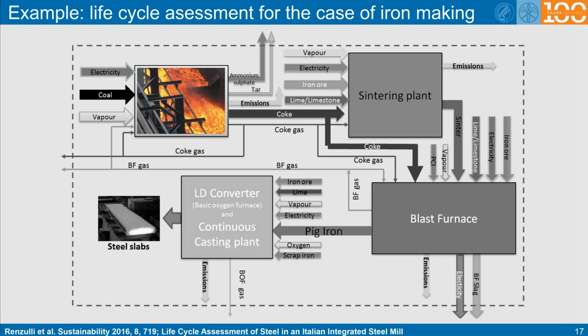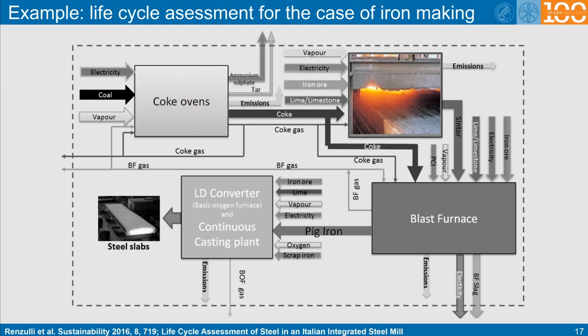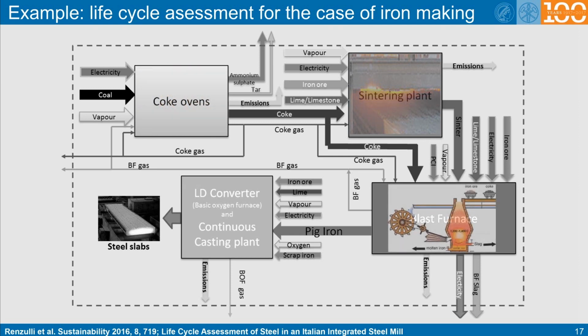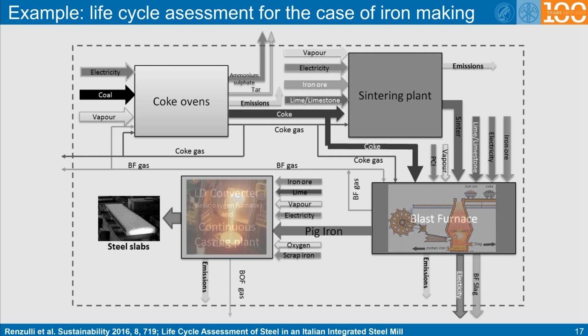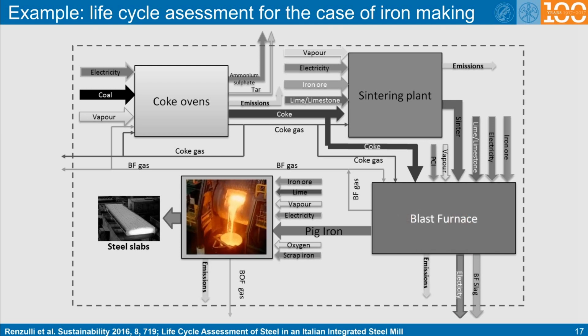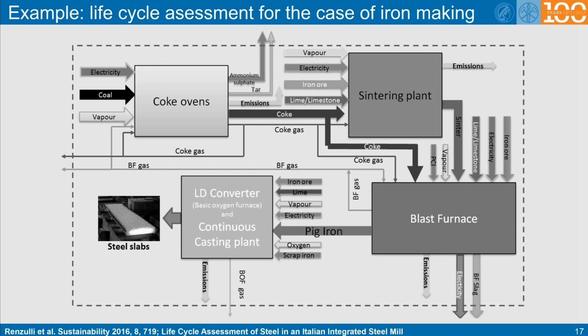This flow diagram shows the input of coal, steam, and electricity that is used for operating the coke oven plant, which then feeds the sintering plant, which in turn is the basis to operate blast furnaces, where the actual reduction of the iron ore takes place. This is also the production step where most of the CO2 is produced. The so-produced iron, which is also referred to as pig iron, is next transported to the steel plant. In the steel converter, the carbon is further reduced by blowing oxygen into the liquid iron-carbon melt. The liquid steel, after having adjusted its desired target composition in the secondary ladle metallurgical treatment, is then cast into slabs that are further subjected to warm rolling. Casting is in integrated steel plants mostly done by using continuous casting machines, often in several parallel strands.